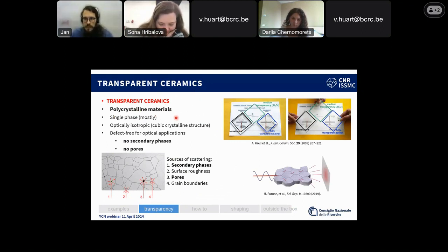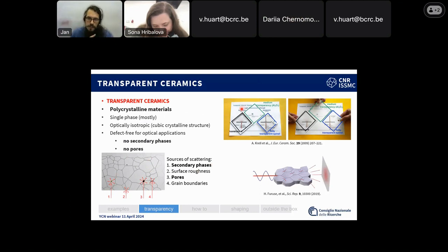If you start reducing the size of the grains, actually what you can see in this graph, or at least I hope you can, on the z-axis, the vertical one, you have transparency, and you can see that from the 0 total opacity, it starts to get up to some reasonable numbers. And what we're doing here is we're going up with the wavelength, and we're going down with the size of, let's say, scatterer, in our case, of the grain.